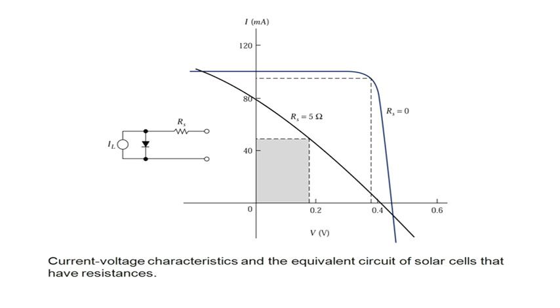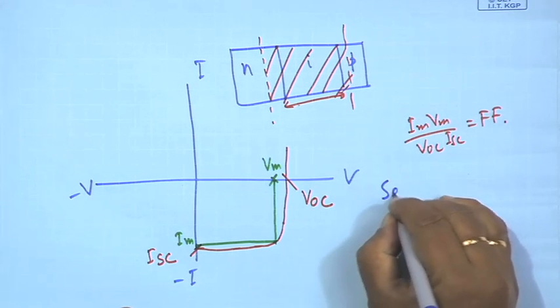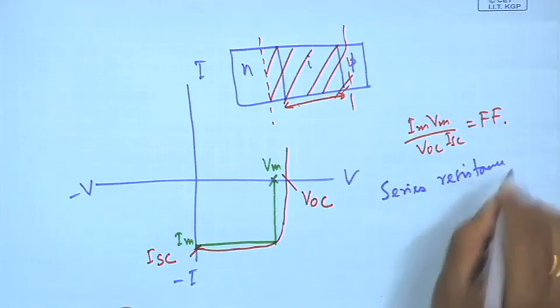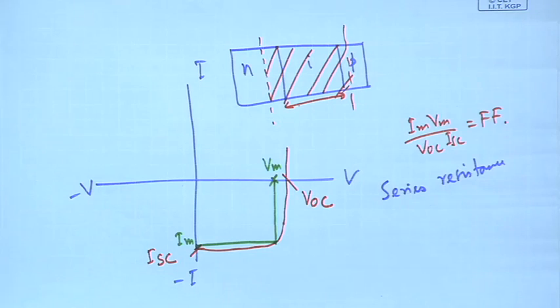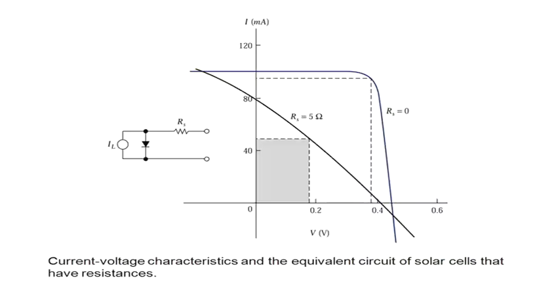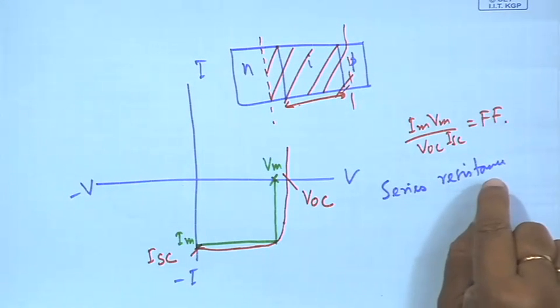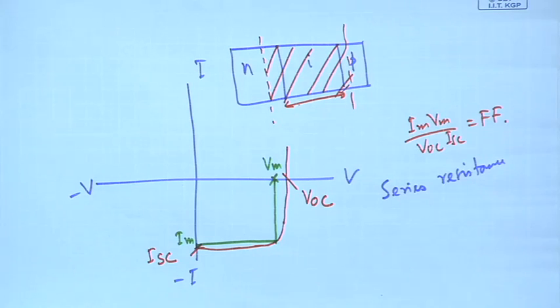Another important thing that we must discuss is the effect of series resistance. The series resistance comes from the finger electrodes we see, and there are other possibilities like the doping concentration between the metal and the semiconductor. So series resistance is a very important parameter in a solar cell. When the series resistance is 0, the characteristic is almost rectangular, this blue one. But when there is a series resistance, say 5 ohm, this blue curve comes down to this line, so a very small rectangle is obtained. As the series resistance increases, the maximum power rectangle becomes smaller, so the efficiency will be very low.